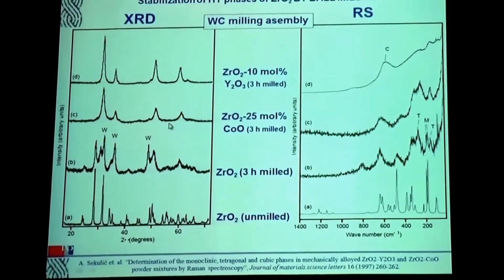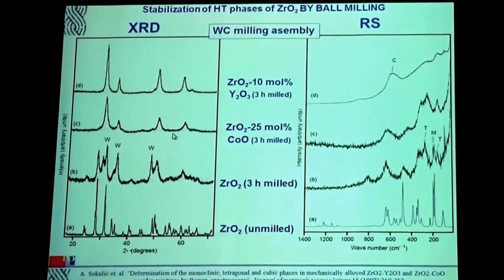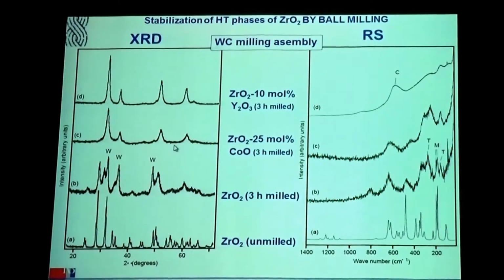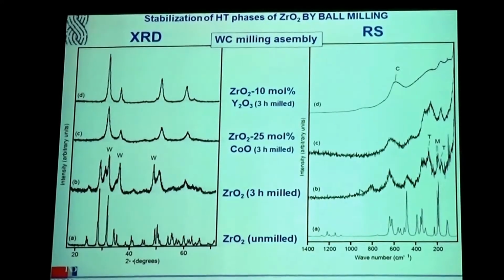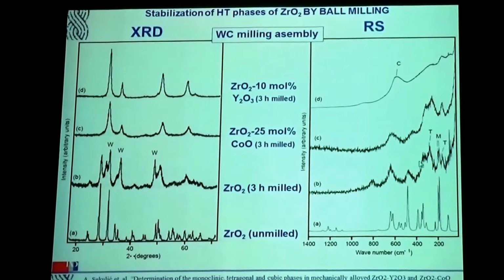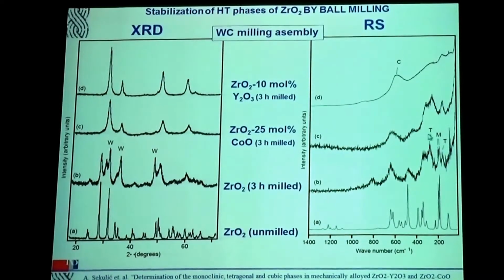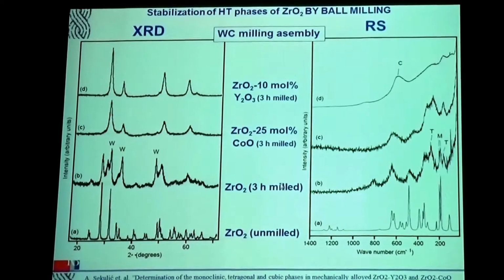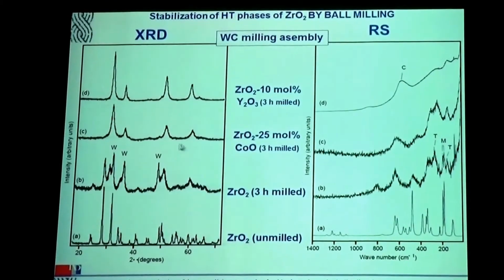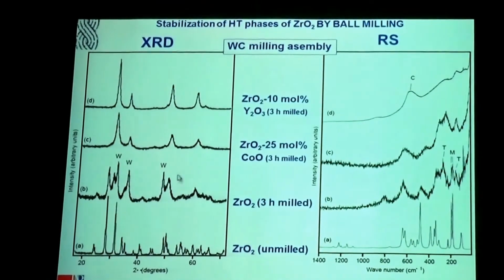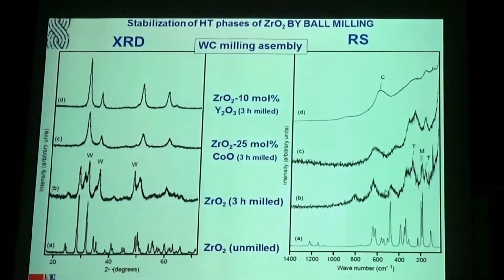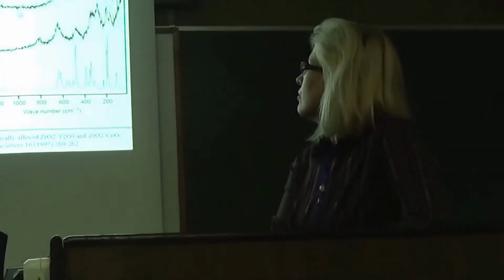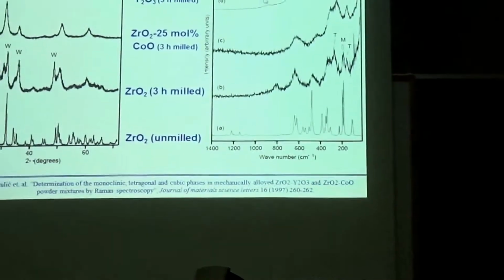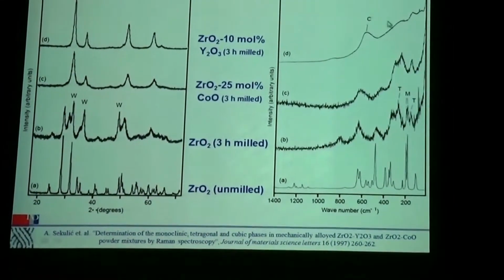X-ray diffraction measurement shows that we have a transition to cubic structure. However, with Raman spectroscopy, we can easily recognize the appearance of tetragonal phase already when we milled pure samples. We actually explain this stabilization by inbuilt tungsten in the zirconium oxide, so actually this is also a stabilization. After addition of cobalt oxide, we have a very good tetragonal structure. However, this other one was cubic.